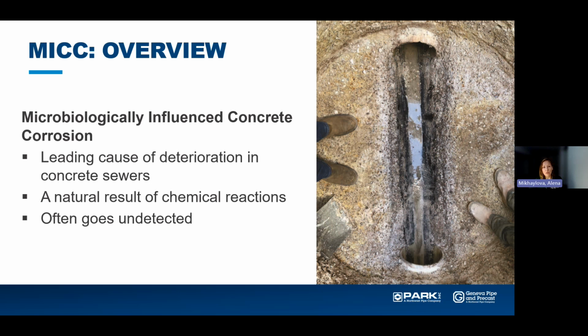So why do we need corrosion-resistant structures in our sanitary sewers? Because the leading cause for deterioration of concrete sewers is microbial-induced corrosion. Over the years, concrete has been used for storm sewers and sanitary sewers, and with time we understood that concrete does not last as long under sanitary sewer conditions and deteriorates much faster than storm sewer structures. That's a natural result of a chemical reaction. Very often it goes undetected because a lot of agencies don't have asset management programs. They don't survey the structures on a regular basis, and they only find out about the problem once they have an emergency, let's say a collapse in a pipe or a manhole.